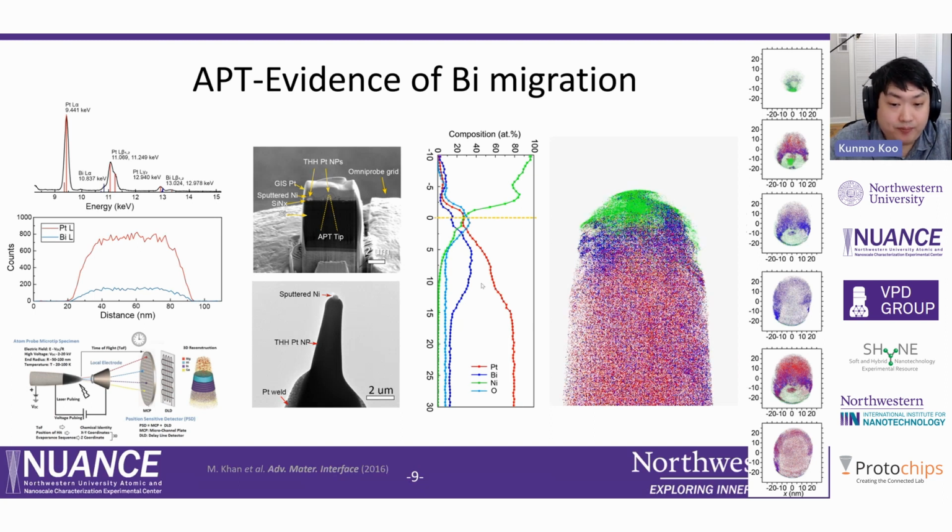The reconstructed model now well describes that there is a distinct segregation of the element at the nanoparticle surface. The bismuth concentration at the top 10 nanometers of the surface is 40%, while the remaining 60% is platinum. However, the bismuth concentration inside the remaining part of the roughly 500 nanometer particle significantly drops to 10%. This result directly shows that elemental segregation happened during the facet development.